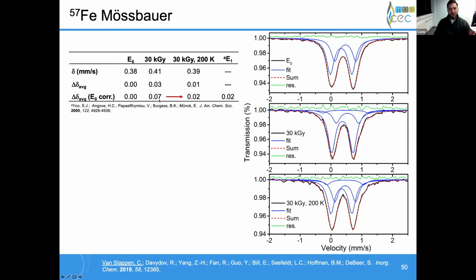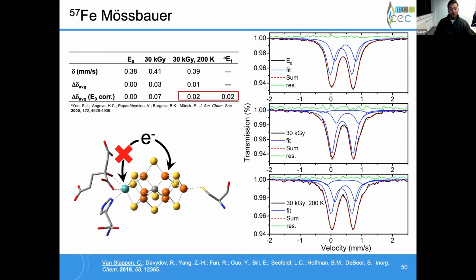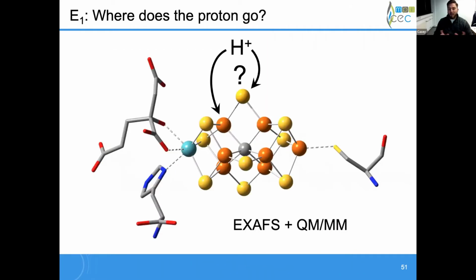And importantly, if you anneal the sample, that shift goes down and it matches that of E1. So now this really supports, together with the XAS, that we do not have molybdenum-centered reduction. We have an iron-centered reduction. It looks relatively localized, and our hypothesis is that the connection between this cryo-reduced state and the E1 state seems to be the availability of a hydrogen. And so the next step here, maybe I'll pause for questions, is where does the proton go?